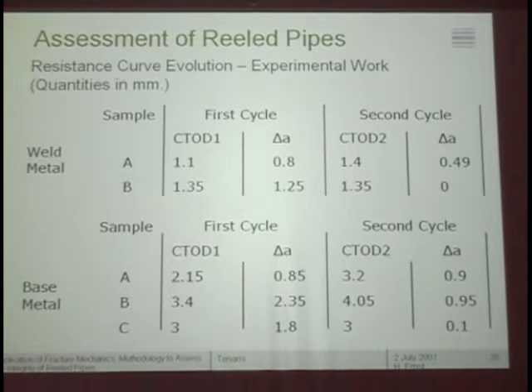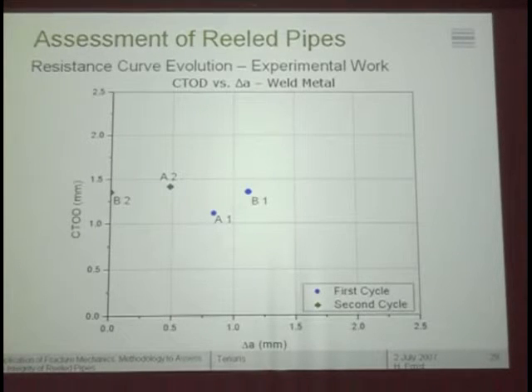We also ran an experimental program to determine this. Basically this is a little busy slide, but bear with me and we will go over it hopefully successfully. We look at this one here first, the weld metal. I'm going to show you just two samples, although we ran more than that, A and B. Let's look at A. In the first cycle we got to a CTOD of 1.1, all quantities are in millimeters by the way, and the delta A was 0.8 for that. In the second cycle we went to 1.4 and the crack extension for that cycle was 0.49. And for sample B, you can see these numbers here. You can complete the table for the rest, but I prefer to show you the slide.